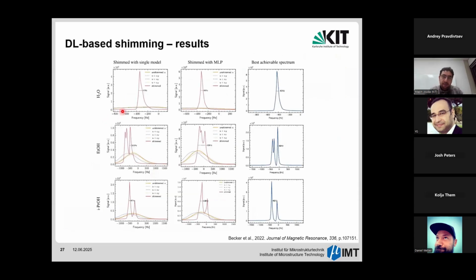And here are some examples. Of course, the sample we used for training data was water. As you see here, this line is the unshimmed spectrum from which the model starts, and already in 1 shot it can predict the correct shim, which is quite close to the optimum that could be achieved by the simplex algorithm. So this is the deep regression. This is the deep regression ensemble, and it's also of similar performance. The interesting thing is that also when we tried different samples that were not used during the training, the model was still able to predict the shims quite correctly.